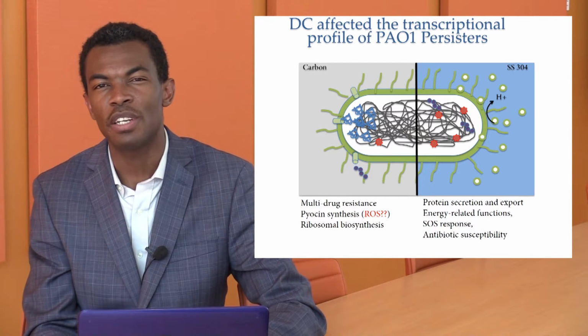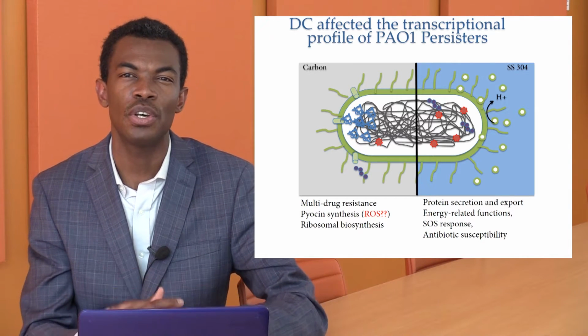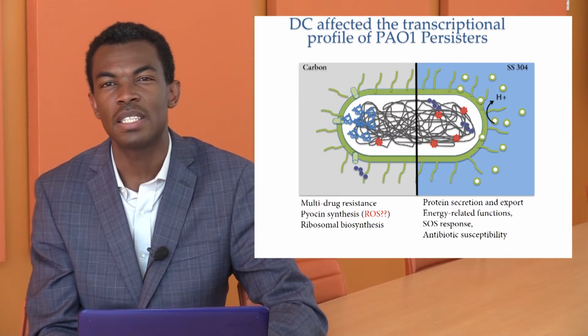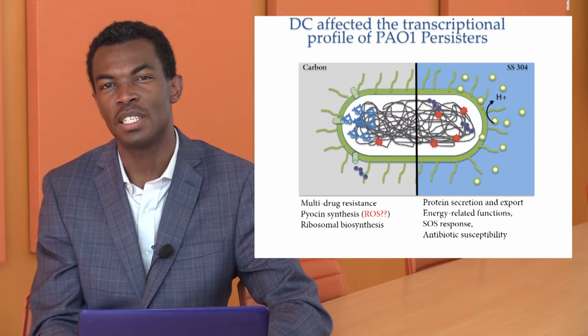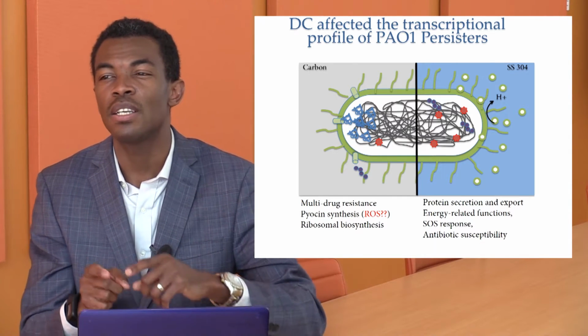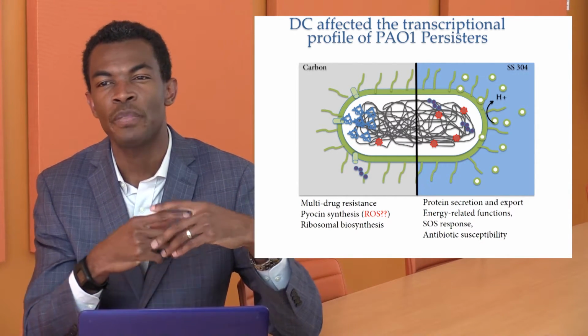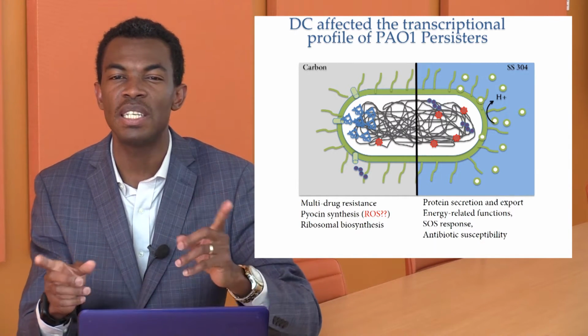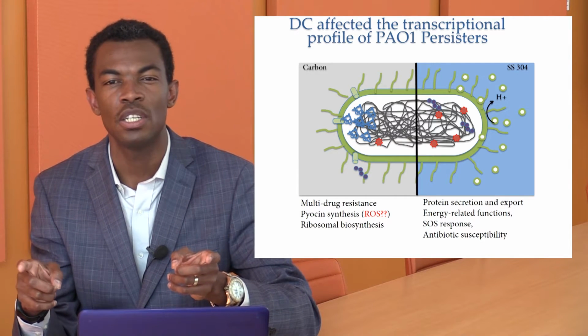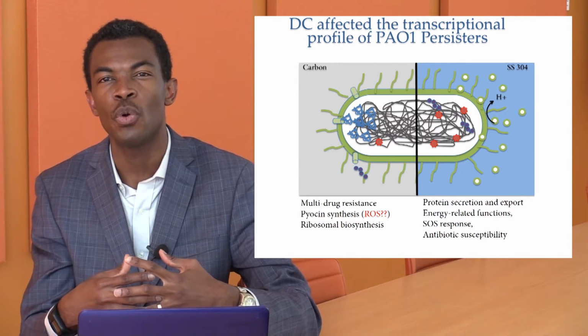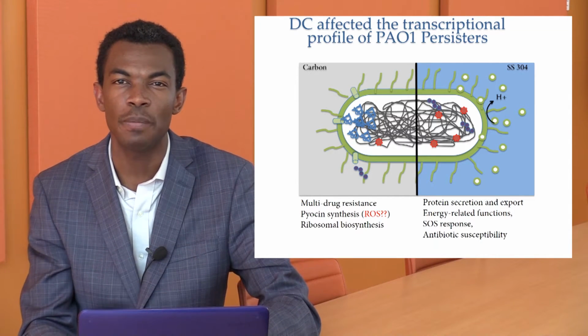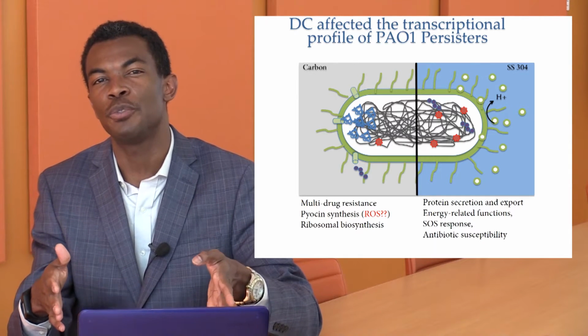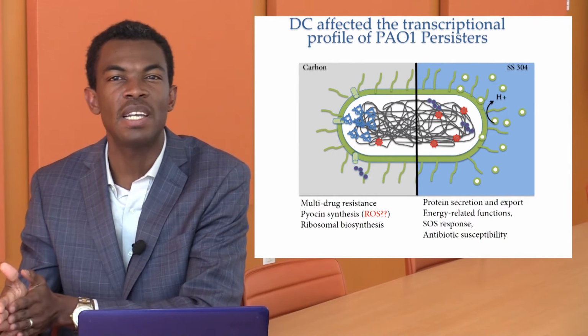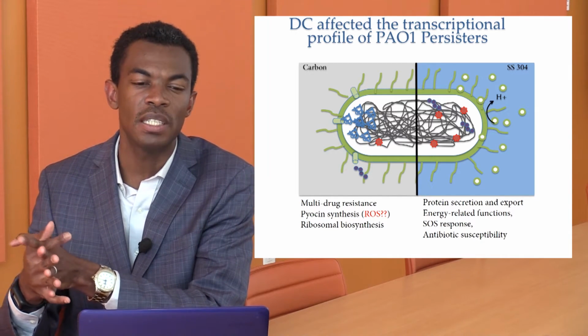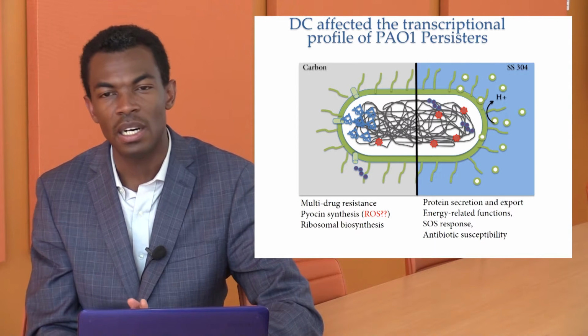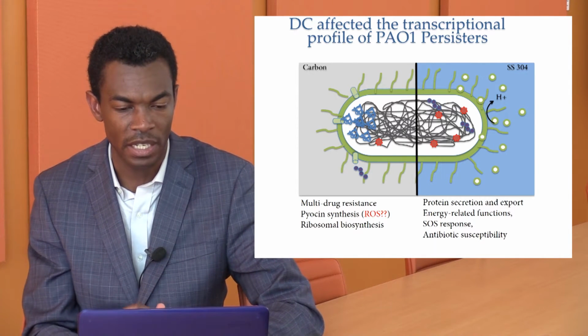But besides that, we also saw that the cells somehow tend to activate resistance mechanisms against antibiotics. So many of the genes involved in antibiotic resistance were also upregulated. And this goes along with our previous data showing that during the treatment with carbon electrode, we didn't see any synergy between the carbon treatment and the antibiotic. Whenever we added the antibiotic at the same time, we didn't have very significant killing, but we have to wait until the treatment is performed using carbon electrode. And then when the antibiotic was added sequentially, we can eradicate all the cells. And this is exactly what this DNA microarray data shows here.